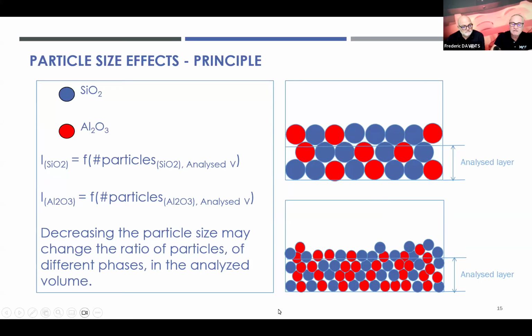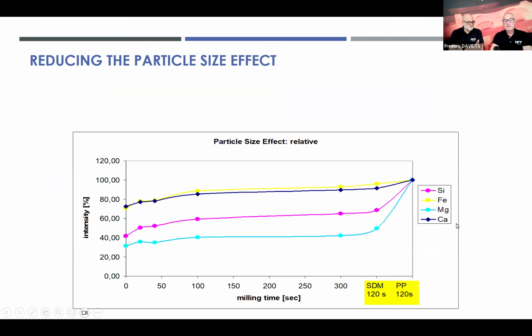So it may be that we have a different amount of particles in our analyzed layer or our analyzed volume, really. So we have to be aware that the measured intensity for each element in our specimen that we want to analyze is a function of the number of particles in our analyzed volume. So decreasing the particle size may thus have a strong influence, but it's something we need to do. Now, how can we reduce the particle size effect?